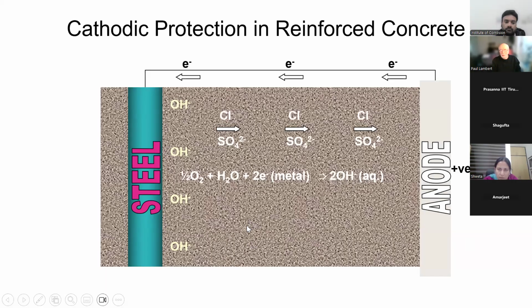So chlorides will go away, sulfate will go away, and indeed hydroxyl ions will be pushed away. So the area around the steel will be richer in hydroxyl ions, but they will be getting distributed, but it will be low in chloride and low in sulfates. And both of those are good things in terms of maintaining the condition of the steel.